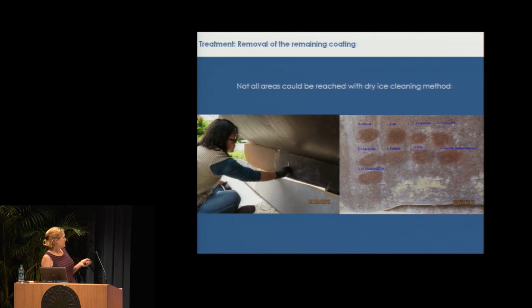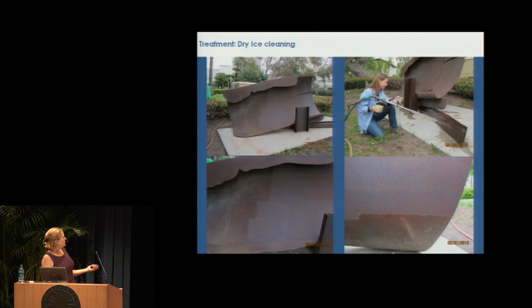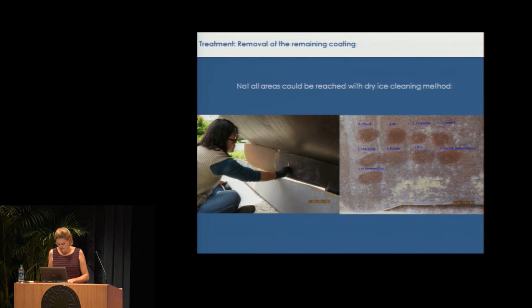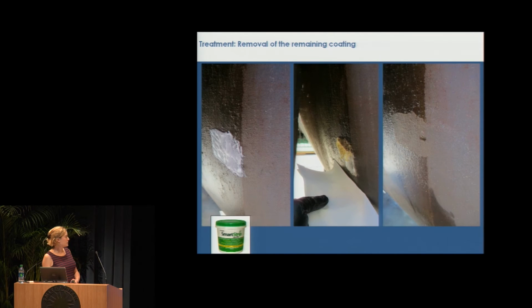The only parts where we couldn't get the coating off were the bottom parts and the parts in between, like here, the back part of that panel, we couldn't reach, so we had to do some further solvent tests, of course. For these solvent tests, my colleague Lily and I did some already before the dry ice treatment. And we figured out that, just like Julie also mentioned, some paint strippers were our best option. So we used the Smart Strip, which turned out okay for the job.